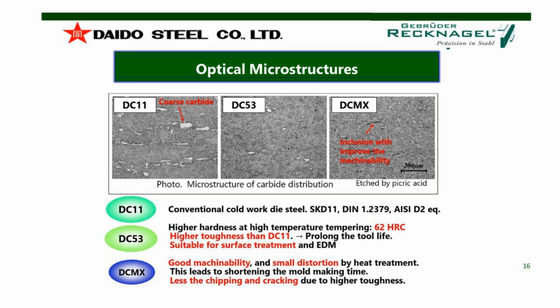Yeah, in the middle, the situation with the coarse carbides is much better than with the D2 grade. We have also some linings, but the linings are finer, and also the coarse carbides are finer. But the situation with DCMX is really much better. You can't see any coarse carbides. You have no linings with the carbides. It looks a little bit like a powder steel